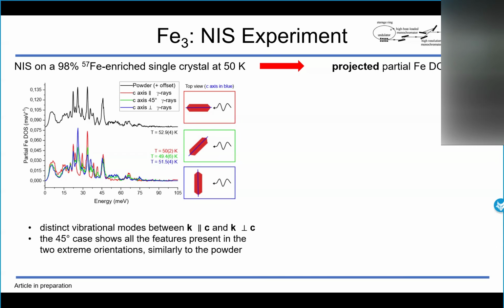So the red line is the experiment with the gamma ray wave vector parallel to the c-axis, while the blue line is with the gamma ray wave vector perpendicular to the c-axis. And we can see that we have different peaks between the two experiments, meaning that we have different vibrational modes depending on the orientations. Moreover, the green line is the experiment done at an intermediate orientation. This has peaks from both of the two extreme orientations. It is similar to the powder, as expected.